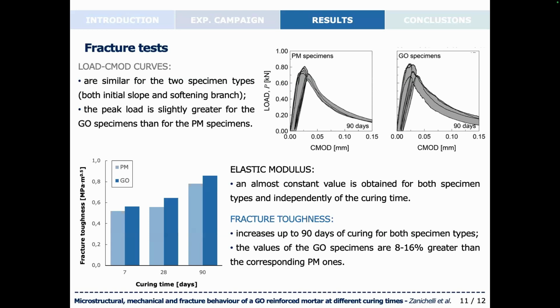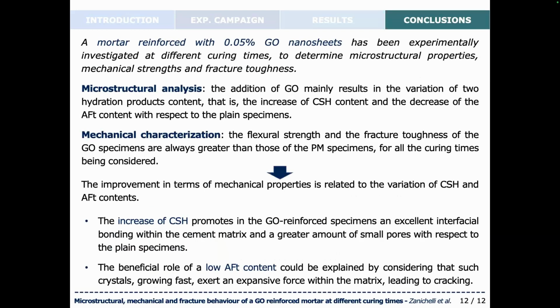And as you can see, this trend is completely similar to the trend we obtained for the flexural strength, even if we consider the shorter curing times. So we can assume that at 90 days of curing, also in terms of fracture toughness, we have reached sort of stable values for both PM specimens and GO specimens. So, and now let us move to the conclusions.